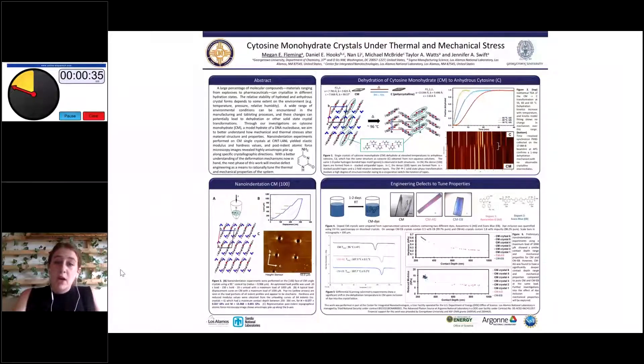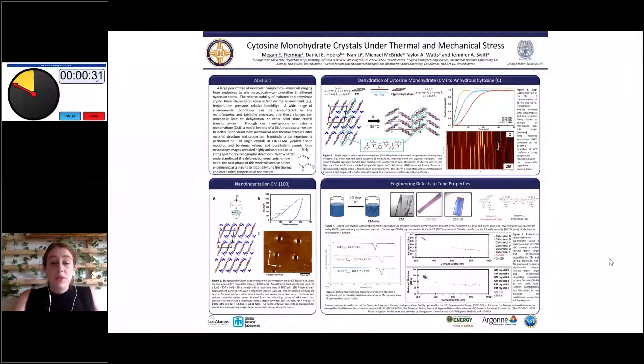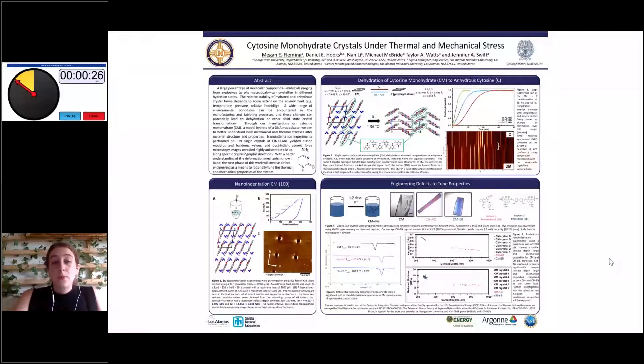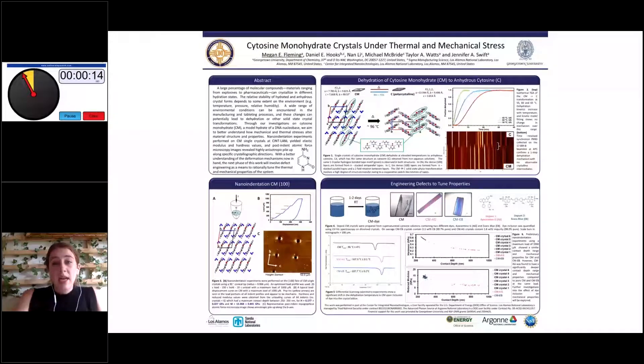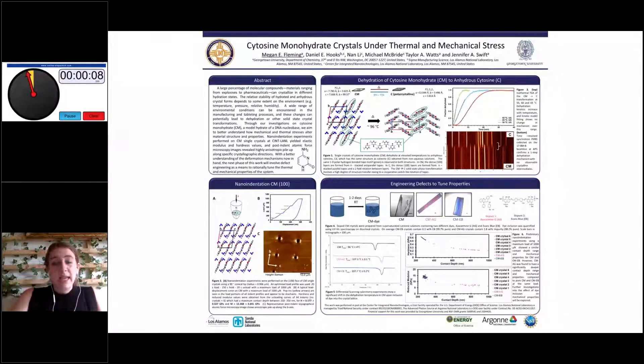Preliminary nanoindentation experiments showed differing mechanical properties: azo-carmine G showed a much deeper contact depth range compared to Evans blue and the pure system, all under the same load of 1,000 micronewtons. These are preliminary studies, and going forward, we want to continue investigating how these dye systems can help tune and engineer specific properties within our crystal systems. Thank you so much, and I'll be happy to take any questions.